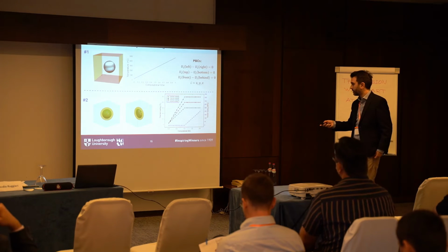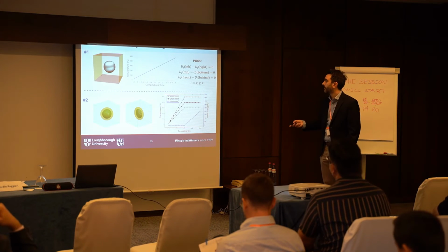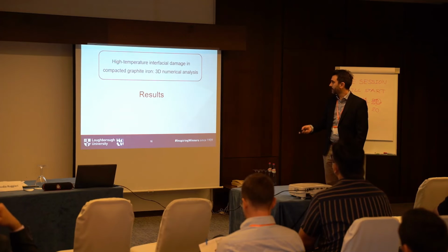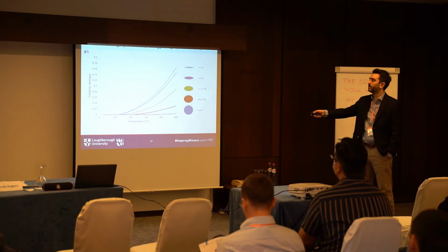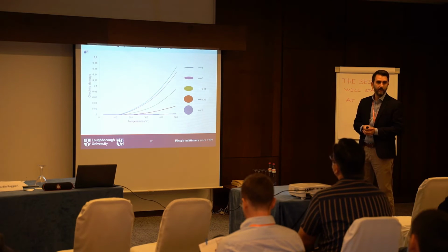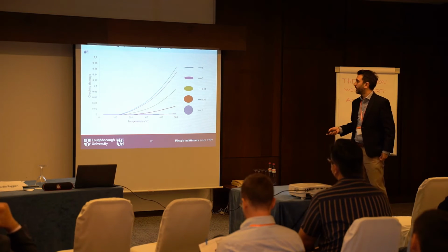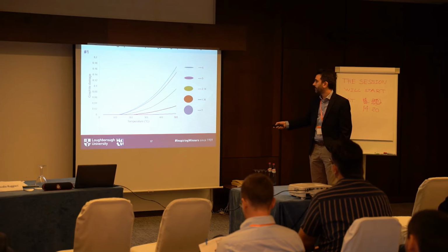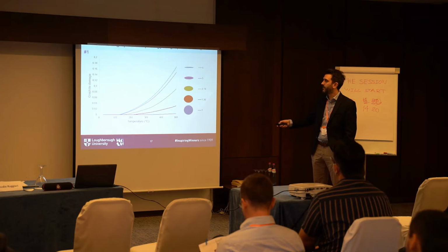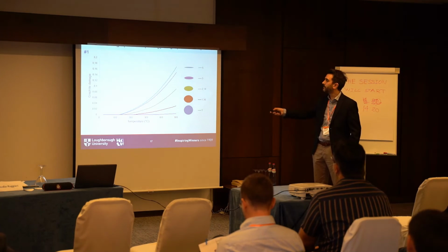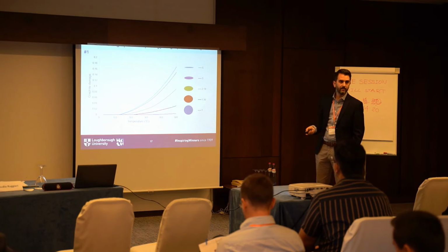Okay? So that was the thermomechanical model in the second case. Let me move then to the results. These are results from the first model, so just heating up the cube. It's no surprise that as we are closer to the circular shape, we have almost no damage. You see this is very small, but as these particles become more elongated, we see a 20% damage.